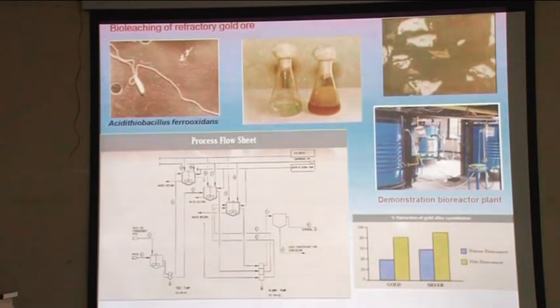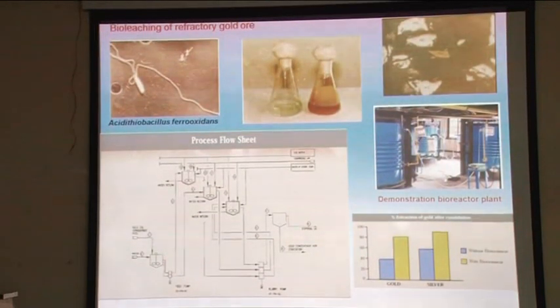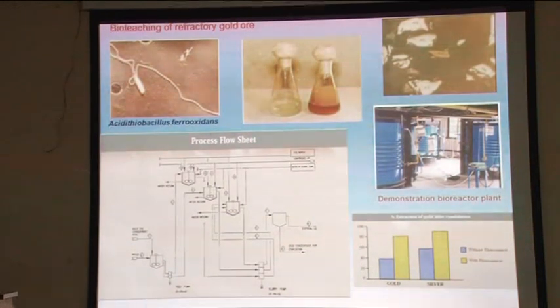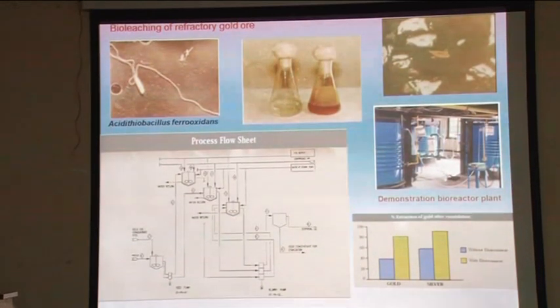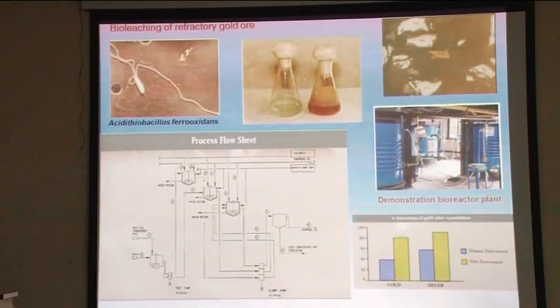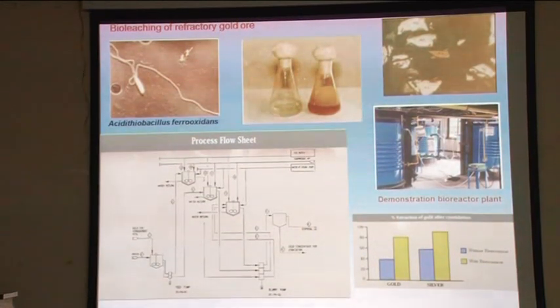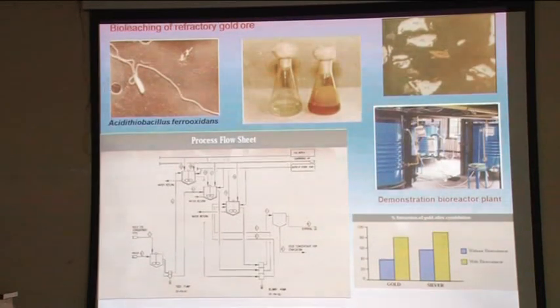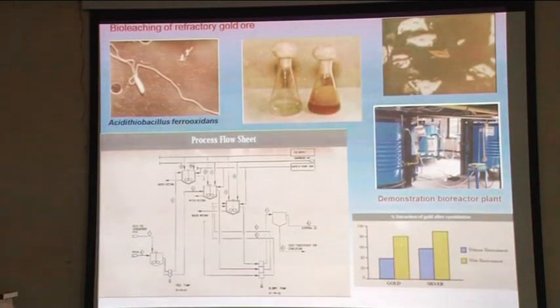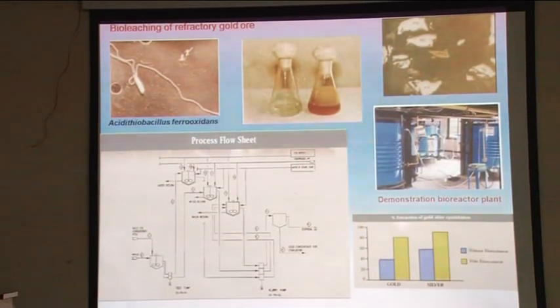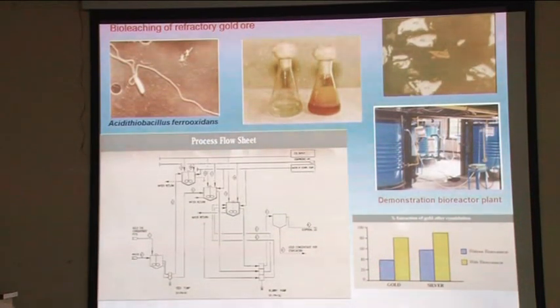And then the leaching is done in the presence of microorganisms at acidic pH. But as we all know, gold is actually extracted only by cyanide, and the cyanidation process has to be done under alkaline pH. So after you get the dissolution of the sulfides, you neutralize using lime or sodium hydroxide, and then you do the cyanidation to extract the gold. On the bottom part of the graph, what you see here is that the gold extraction in the absence of the bio-oxidation process is about 40%, whereas it's almost doubled when you do this pre-oxidation of the sulfides before you do the cyanidation.